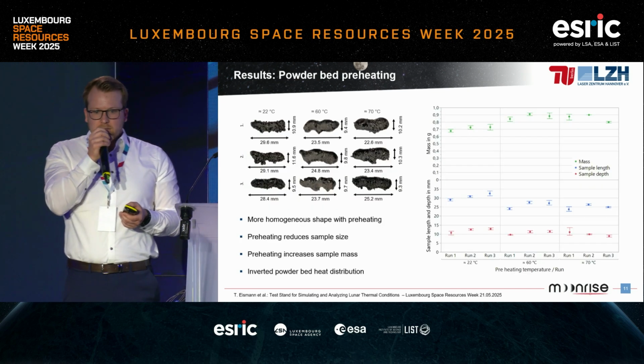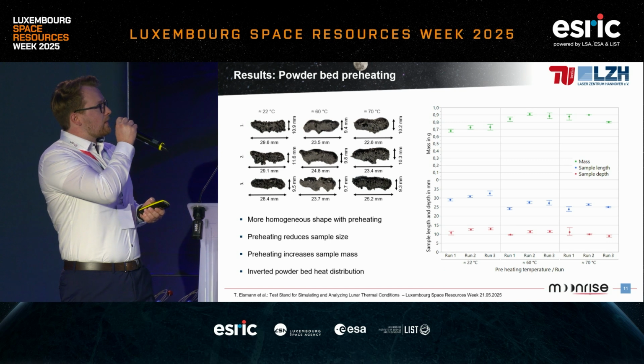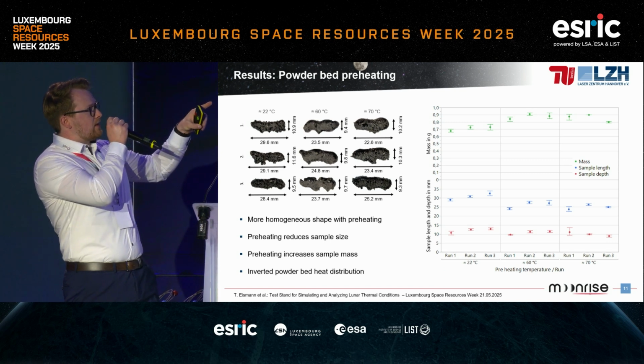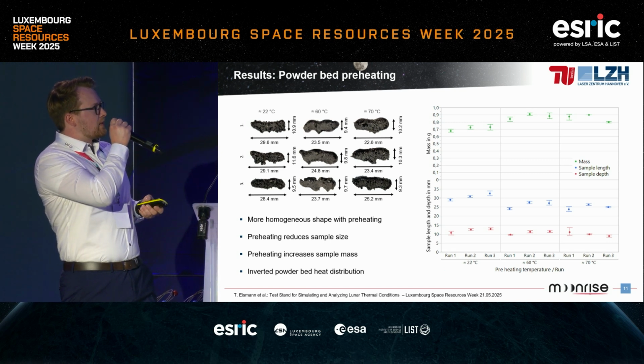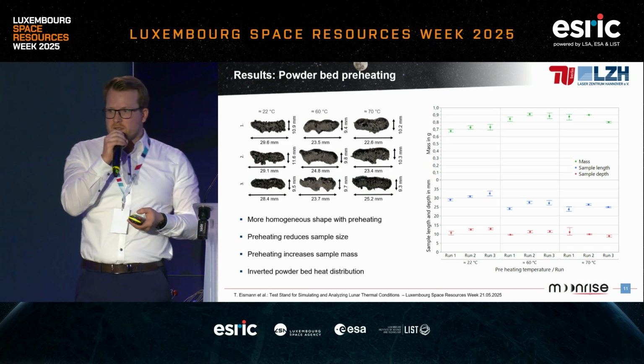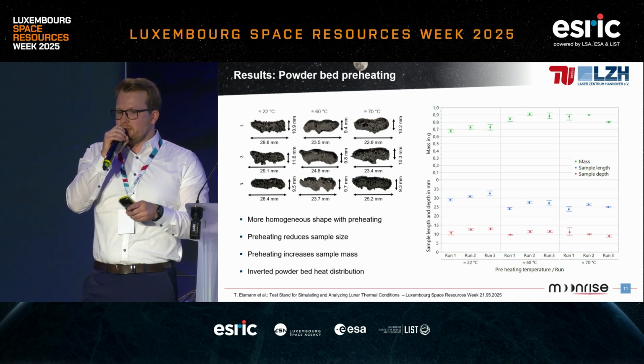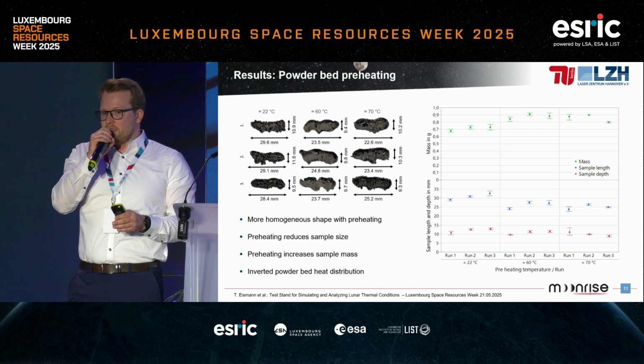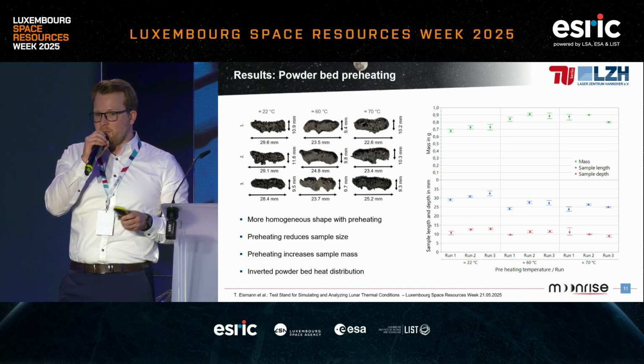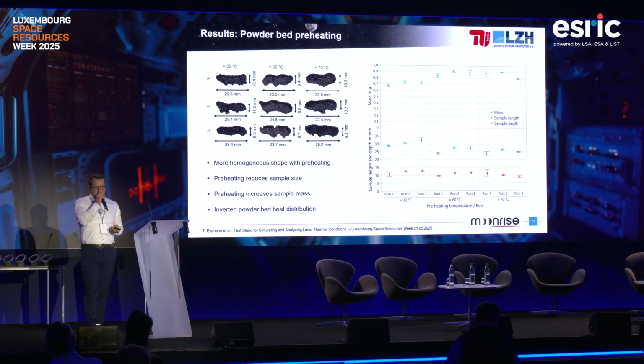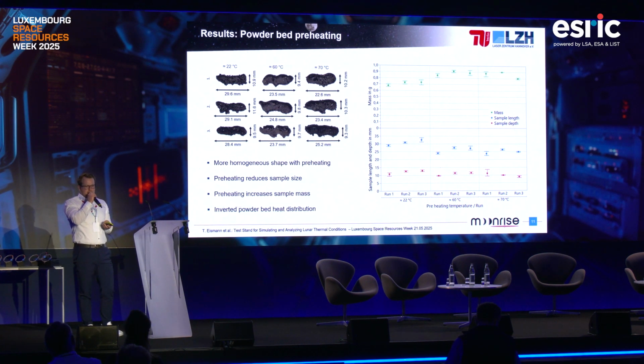We can see that at the elevated temperatures of 60 and 70 degrees Celsius, the shapes are more homogeneous on the surface. There's not much of a difference between these elevated temperatures, but there's a difference compared to the samples with ambient temperature. And if we look into the data, we see that with elevated temperature, the mass of our samples is higher and the dimensions are lower, indicating that there is a higher density inside these samples.